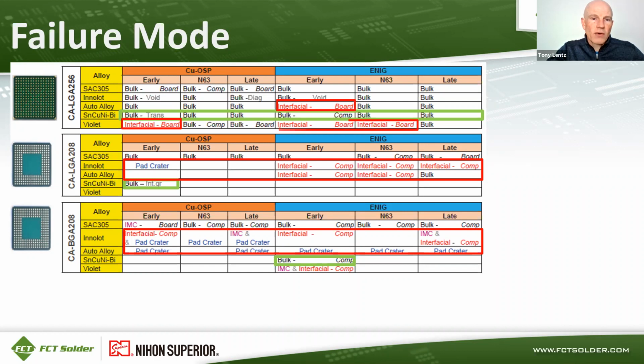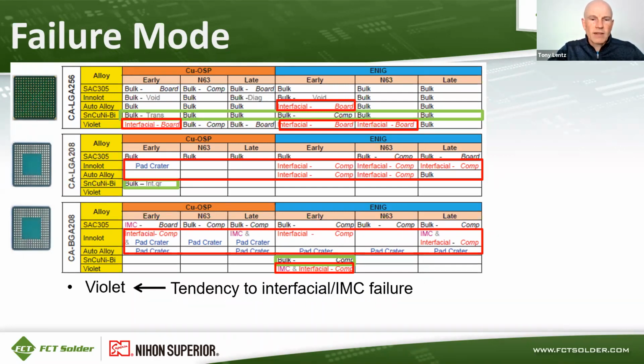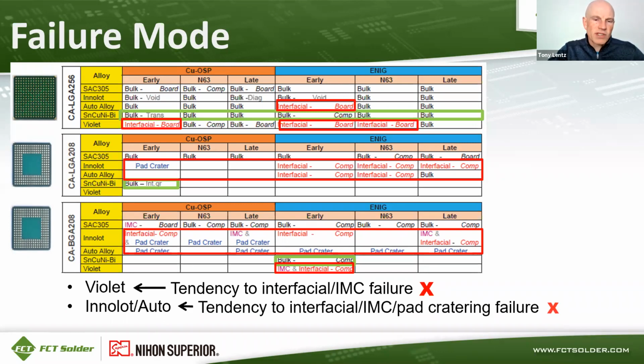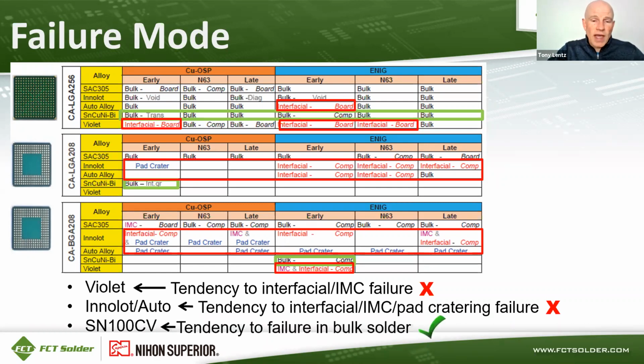And then some of the other alloys that were tested, like Violet, had interfacial and IMC failures. So Violet tends to fail at the interfacial or IMC interface. Innolot and the other automotive alloy that was tested tended to fail with a mixture of failures, had some interfacial failures, some IMC failures, some pad cratering failures. SN100CV mostly had a failure in the bulk solder.